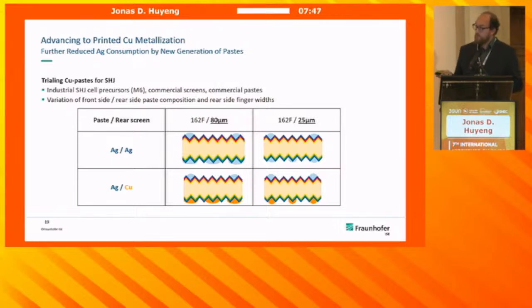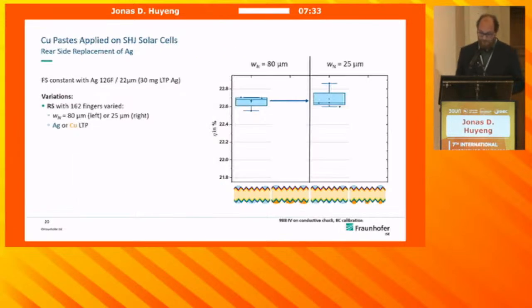So here's a similar experiment. We have a reference group with both sides silver, and then 2 different screen openings. So the first group has an 80 micron opening on the rear side, the other 25 micron. The front side is the same for all groups. And then you can see, if you look at the IV data, here only in terms of the efficiency, for simplicity, you can see that for silver, it doesn't really matter if you print it with 80 or 25 microns. This is already a really good optimized grid.